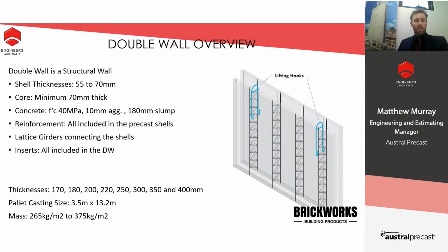Austral Precast has a maximum pallet casting size of 3.5 meters by 13.2 meters for a standard double wall, with masses ranging from 265 kilograms per square meter of panel up to 375 kilograms per square meter, largely dependent upon the thickness of the shell, going from 55 to 70 millimeters.